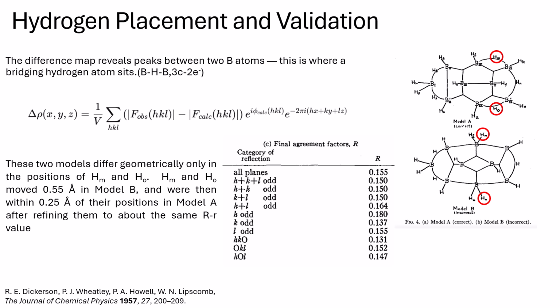After obtaining the boron skeleton, now it is time for placing the hydrogen atoms and figuring out the complete structure, which is also the most important part of Lipscomb's work. The configuration of hydrogen atoms is confirmed with the computation of the difference between the observed and calculated Fourier maps. These maps revealed peaks corresponding to the missing atoms, here the hydrogen atoms. It also includes those bridging positions which form the three-center two-electron bonds.